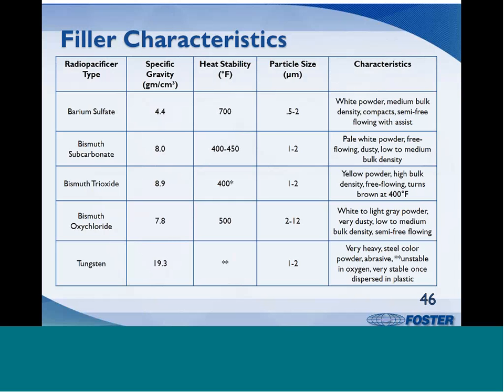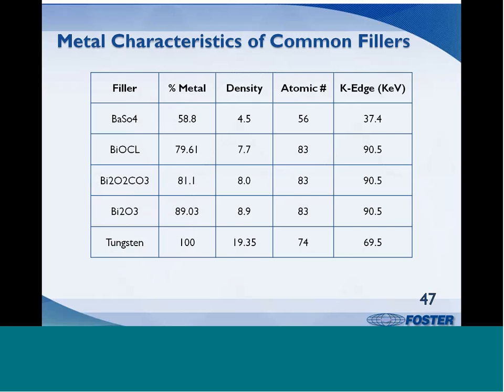Some of the key physical properties for the 5 most common radiopaque fillers are summarized in this chart. The most striking difference is an increase in density when moving from barium sulfate with a specific gravity of 4.4 up to tungsten with a specific gravity over 19. The energy required to unbind a K-shell electron is shown in this table. The K edge values are for the metal component of the compound.